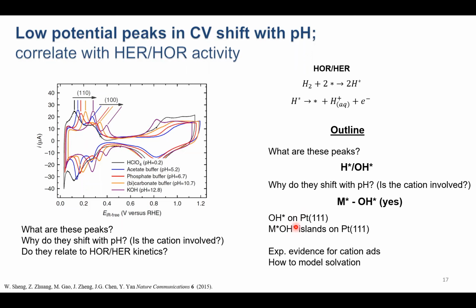And something I'm really excited to show is we actually find a cation, it's not actually an alkali metal cation, that interacts so strongly with adsorbed hydroxide on platinum that it produces cation hydroxide islands on the electrode surface. If I still have time, then at the end of the talk, I'll very briefly discuss some additional indirect experimental evidence we have for this kind of cation adsorption and make some comments about how to model solvation in density functional theory.